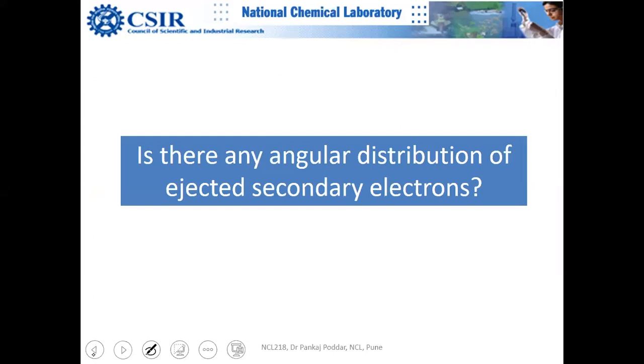There are two reasons behind the origin of the detector placement question. First, where to put the detector. Second, the elastic interaction between primary beam electrons and sample atoms — from elastic interactions you can calculate the angular distribution and scattering cross-sections. For inelastic interactions, however, you cannot predict a simple cross-section because secondary electrons can take random paths with multiple collisions during ejection.